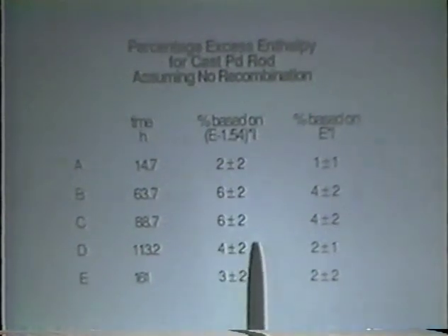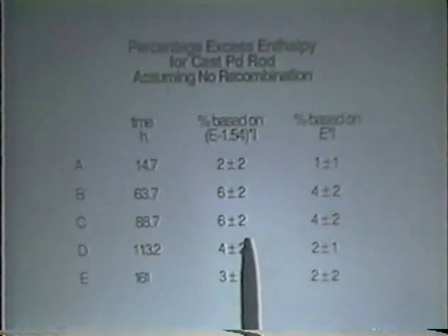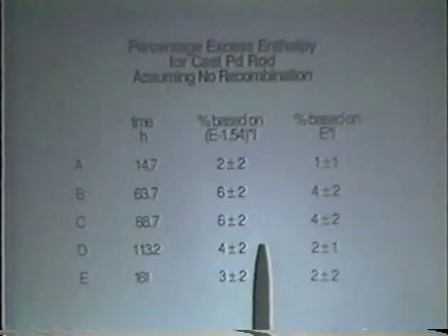We don't absolutely know for certain that this is not excess, but the light water controls have also run typically 4 to 5% excess, or what you would expect. I might also point out there's a paper in the literature in 1958 by a well-known calorimetry scientist, Abner Brenner, at the National Bureau of Standards. And in a cell, even with a separator between a platinum anode and a platinum cathode, he found excess powers of the order of 5 or 6% because of small amounts of recombination.